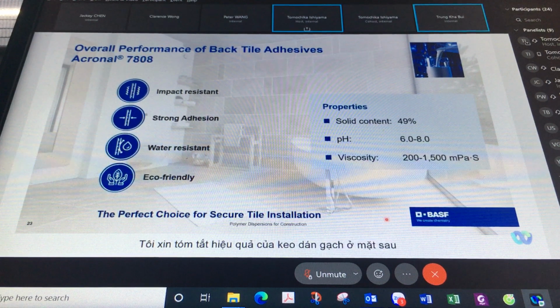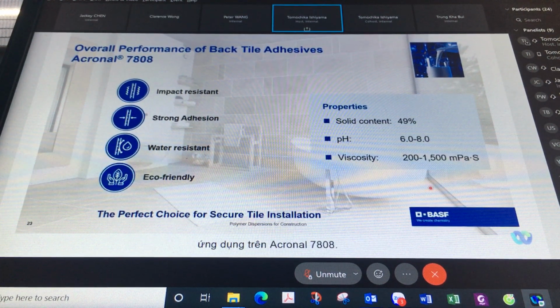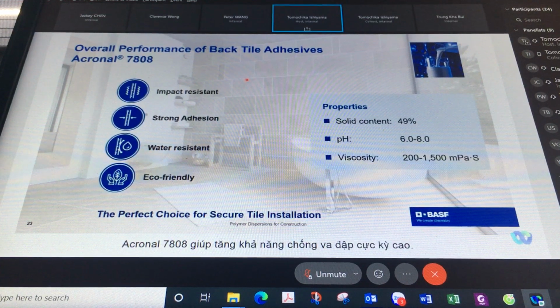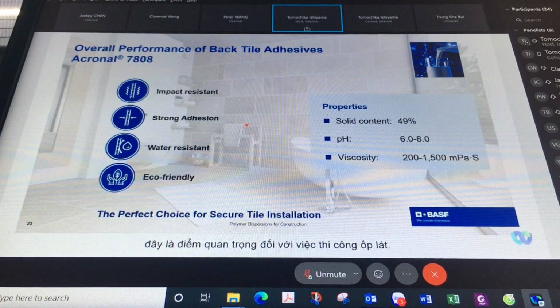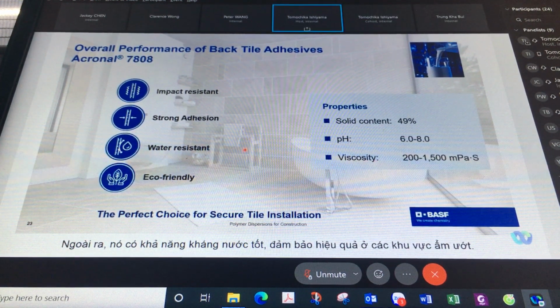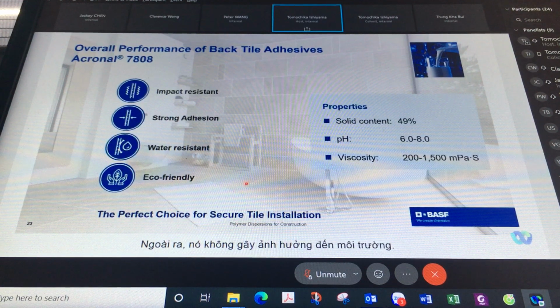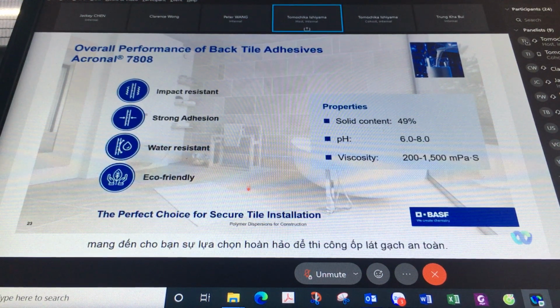Now, let me summarize the performance of back-tile adhesives based on Acronal 7808. As you have seen, Acronal 7808 can add an extremely high impact resistance to hammering. It also enhances the adhesion at the back surface of the tile, which is a critical failure point for tile installation. Also, it has good water resistance, ensuring the performance at wet areas. It does not compromise on the environment. It is free of APEO, ammonia, and formaldehyde, making it the perfect choice for secure tile installation.